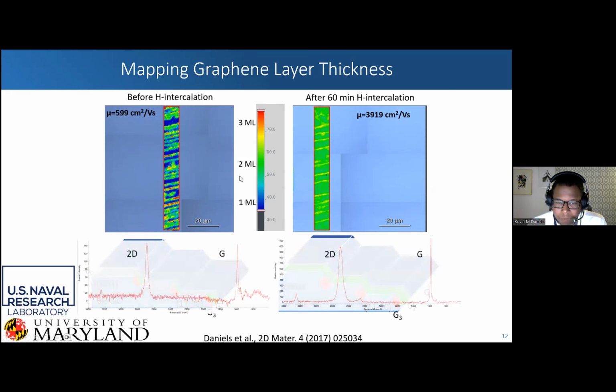tremendously. We can also look at the Raman, and you can see even the Raman peak intensity is much higher because we've separated ourselves from the silicon carbide substrate. All of this is to say we have a very nice material to play around with, and there's some really interesting physics that comes about by releasing it from the silicon carbide and having it quasi-freestanding.